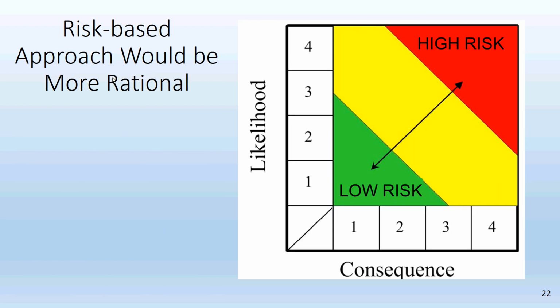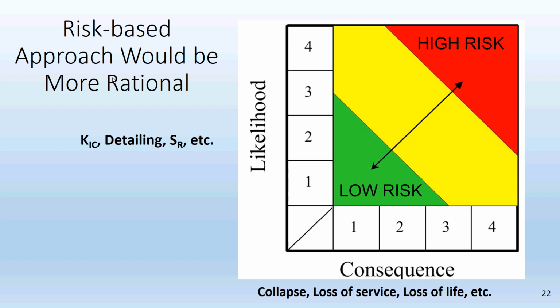Risk is likelihood and consequence. So in terms of the likelihood of a fracture, if we could start thinking this way, those are things I can control, right? I can have very tough material. I can use really good details, right? I don't use details prone to brittle fracture. I can have low fatigue stress ranges, right? I can do all that in design. And so I can make the likelihood of the event very small. Now, the consequence, that's presuming it happens, presuming, say, a fracture occurs, no matter how unlikely, what's the consequence? Well, that's things like collapse, loss of service, and so forth. You can put what you want in there, but that's consequence.